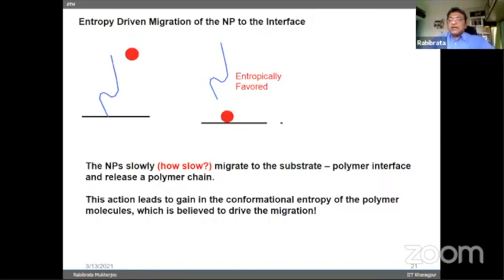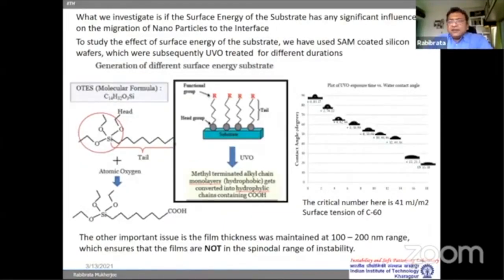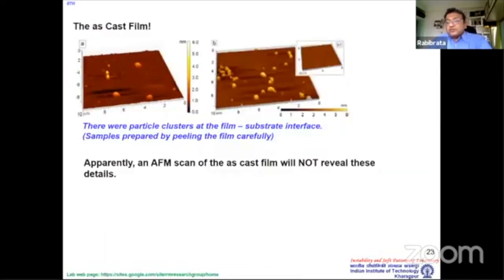Beautiful physics is there. So we also looked into this again in collaboration with Karim's group. One of my students, Sudeshna, spent about 3 months there in Akron. Karim was then at Akron. And so we looked into these dewetting phenomena on surfaces with particle containing films, on surfaces with different surface energy. And we showed that there is actually a non-trivial contribution of the surface energy also, which at times can actually override the entropic effects.